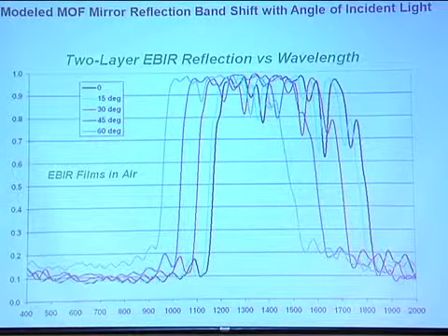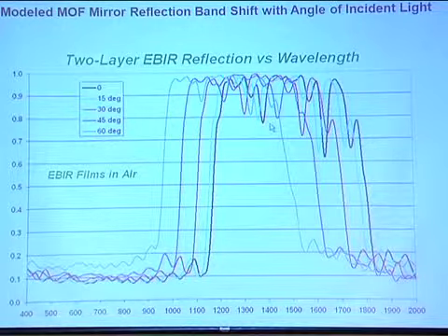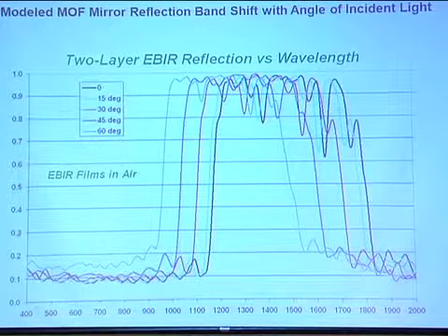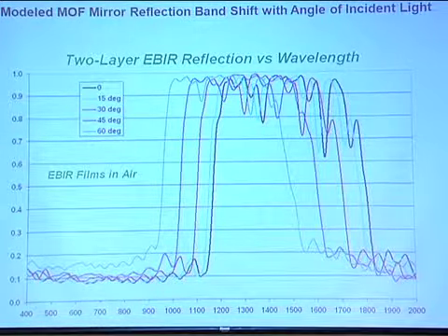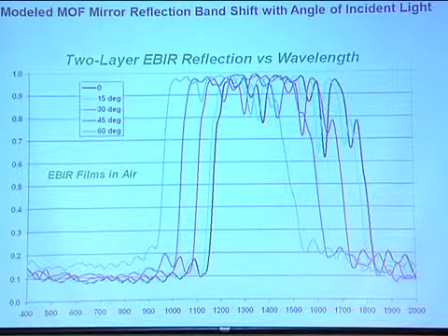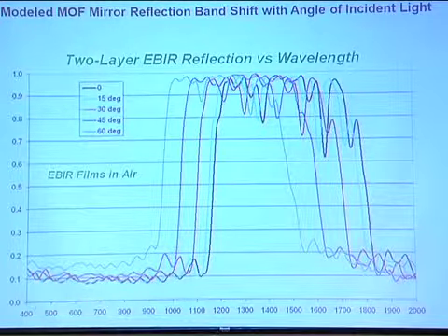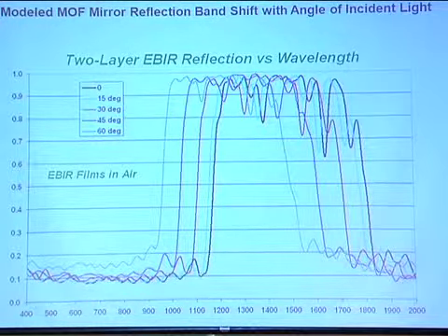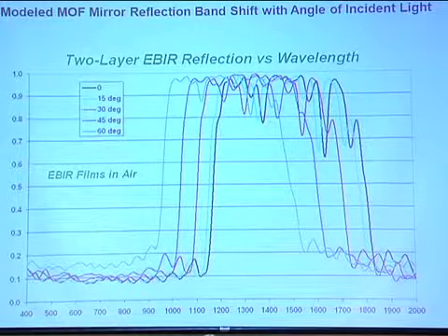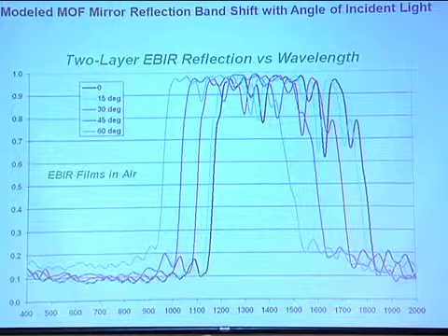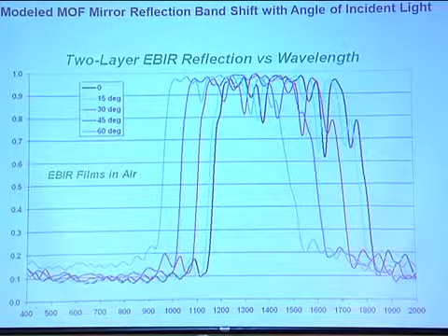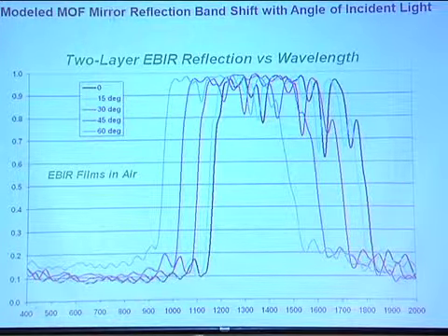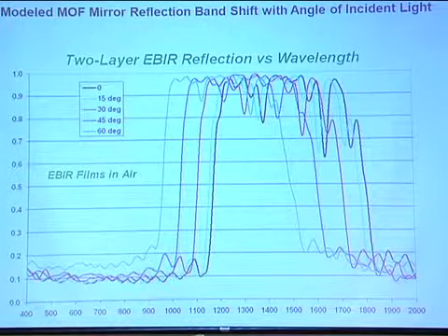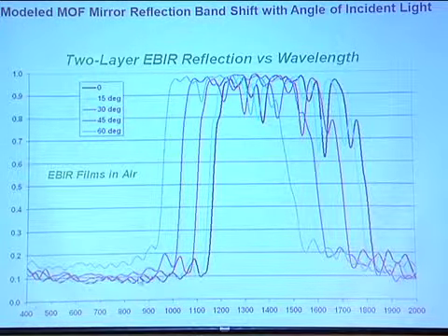Another interesting characteristic of these films is the reflection band shifts with angles. So at normal angles, you'll get a reflection band that is, say, in this case, this is an infrared mirror for putting on windows. So it'll reflect 1100 to 1800 nanometers. As you go off angle, that reflection band shifts to the left. And for a window film where you don't want to reflect any visible light, you want to put that reflection band far enough out in the infrared that when it shifts to the left, it stays in the infrared, and the left band edge here stays above the visible light region, which is 400 to 700 nanometers.